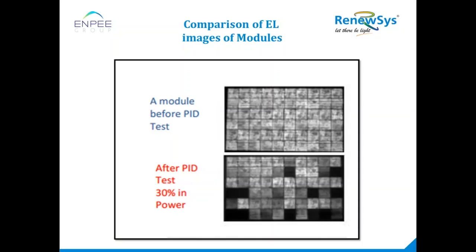And in case you still feel that negative grounding is not possible, it is recommended to go for PV offset boxes, where the solar module functions normally for power generation, or current generation, during the daytime. In the nighttime, the polarities between the junction box and the frame are reversed so that any effect related to PID is sorted out.